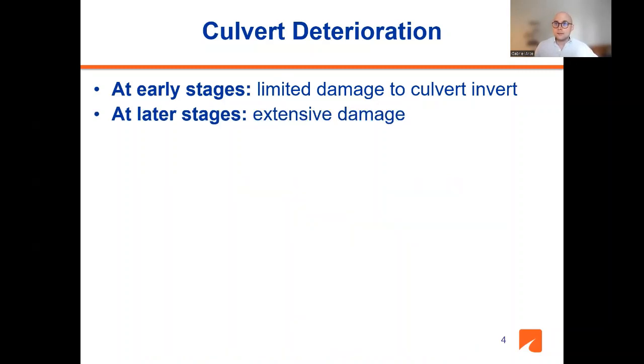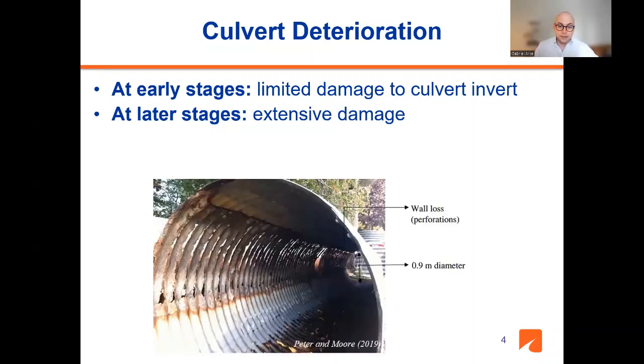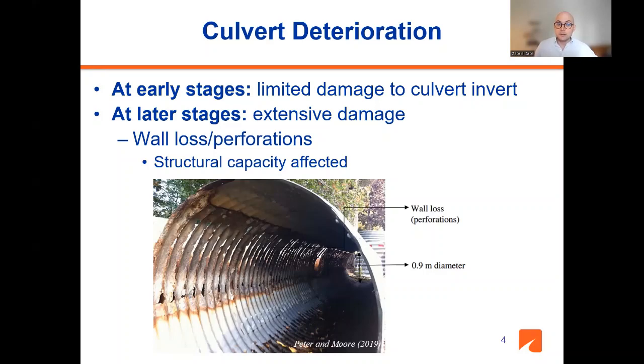Next, at later stages, if nothing is done, extensive damage can occur. This image is from research done by Peter and Moore. This is a culvert that was extracted from the field, and then they rotated the culvert so that you could appreciate all that damage. As you can see, you have wall loss and perforations, and the structural capacity of this culvert is significantly affected. So again, if we do not repair these culvert inverts, this damage can extend and can be very problematic.